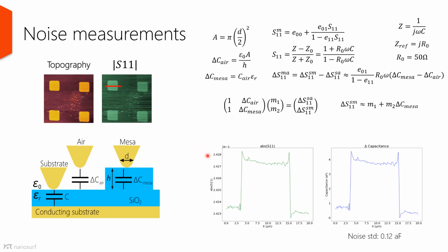For this calibration, we would make 3 measurements of the S11. One on the substrate, one on the mesa, and one in air above the substrate, but at the same height as the mesa. Then we would use the difference in S11 between air and substrate and mesa and substrate and build a similar but simpler system, because now we're looking for a linear relationship between the S11 and the capacitance, and we're only interested in the change of it. And it turns out that this step in S11 is equal to the step in the capacitance of 4 attofarad, and the standard deviation on top of the mesa is 0.1 attofarad. In this standard deviation, of course, there is also a contribution from the topography, so the real noise of the electronics is even lower than that, and usually is measured on a zero-length scan.